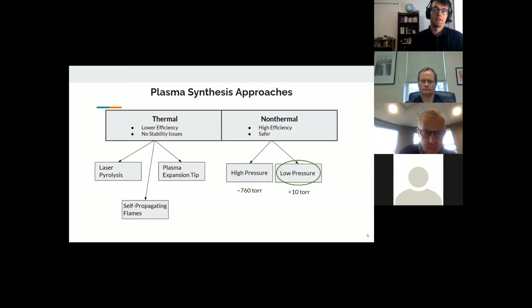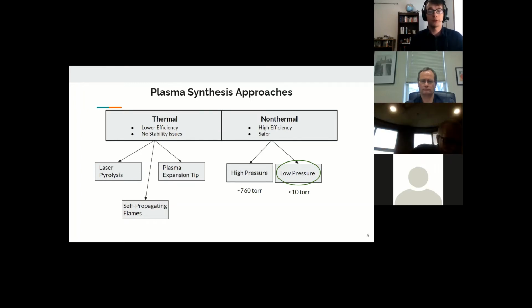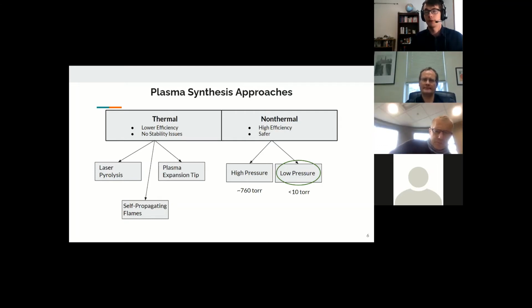Another thermal plasma synthesis technique that's been used for silicon carbide is the plasma expansion process. The experimental configuration of that process consists of a DC plasma torch into which the precursors are fed, followed by a chamber for nanoparticle collection. Generally, the DC plasma source requires a very high power to sustain the plasma. Some sources cite that it requires 100 or more amps and 20 or more volts to sustain the plasma, as the only plasma coupling is through the direct breakdown of the media, in a similar method to welding. So there's an arc that's struck, and the nanocrystal reaction takes place in that arc.